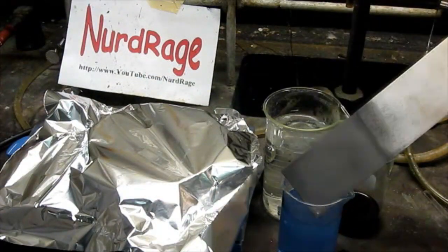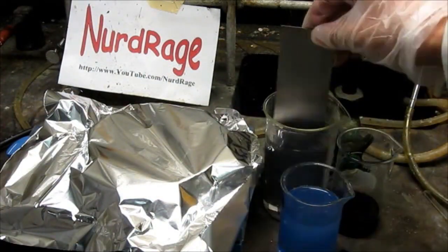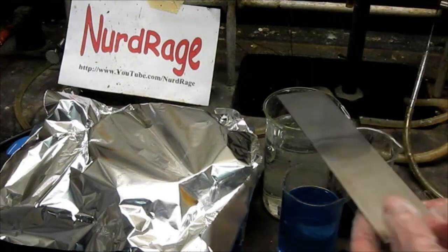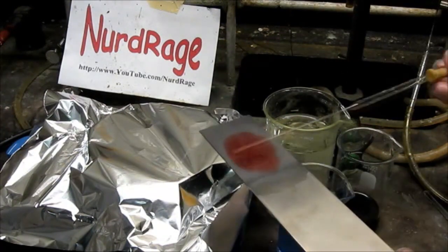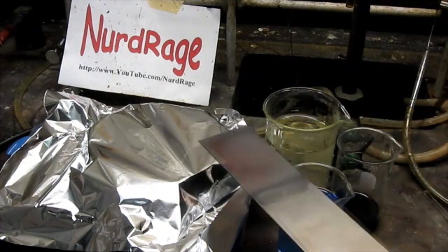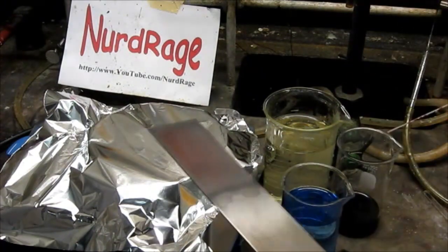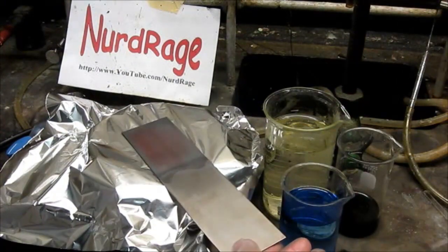Here is our activated titanium surface etched by the acid. Give it a quick rinse in water to get off the acid. Now place onto it a thin layer of cobalt nitrate solution. Drip off any excess. Now place it onto the hot plate and hold it down with a glass rod for